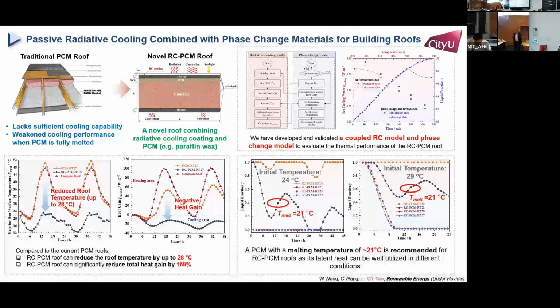And then we are also working on radiative cooling combined with traditional phase changing material, such as paraffin wax, because the existing passive phase changing material rooftop lacks significant cooling capacity, and the performance may be even weaker when the PCM is fully melted. So we propose to combine the PCM together with passive radiative cooling on top of the PCM in building applications. We have developed a two-layer radiative cooling and phase changing material model, and the model is